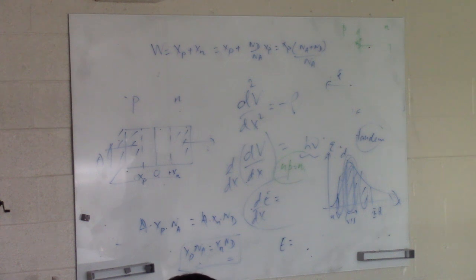But I think he managed to get maybe 10 to the power 15 defects per unit volume. So that is still pretty high compared to silicon, where we can make almost no impurities, right? But even this was good enough to give enough light out.